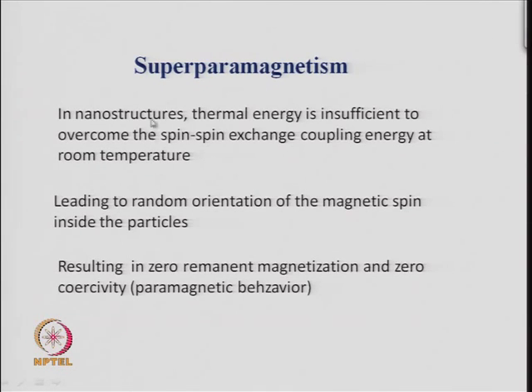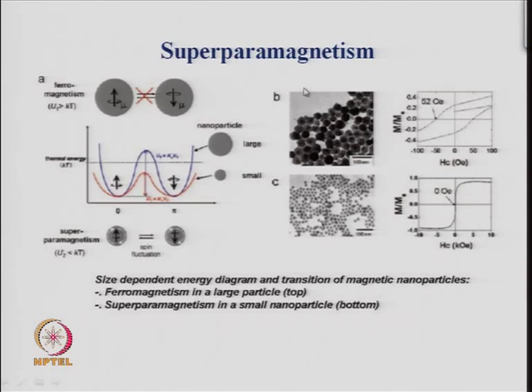behavior. Since it is a particle and not an ion or a molecule, we call it a superparamagnet. That means several molecules or ions together form one magnetic vector, which is randomly oriented inside the particle. So, you can see here in this plot the difference between a large particle and a small particle. What happens is, if you have two vectorial directions, suppose this one indicated by mu has a vector pointing upwards, and here it is pointing downwards, and if you cannot go from here to there, that means you will have some net magnetization, and this is ferromagnetization, when the exchange energy is greater than kT.